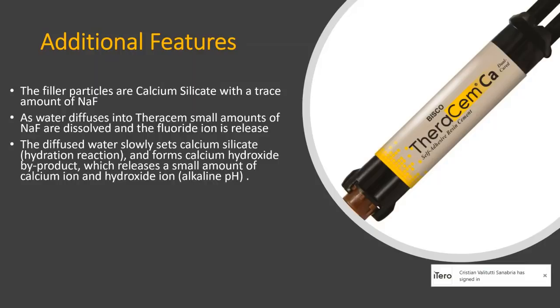And the diffused water also starts to set with the calcium silicate, and what forms is a calcium hydroxide byproduct. And what happens then is you get a calcium ion, which can interact with the saliva and potentially make new apatite. And you have a hydroxyl ion, which is alkaline. And anything bioreactive has to be alkaline in nature. So if you have acid attacks, the studies have shown, and I'll get to it, that you actually will have more calcium release because of the hydroxyl ion and the interchange of the calcium silicate.